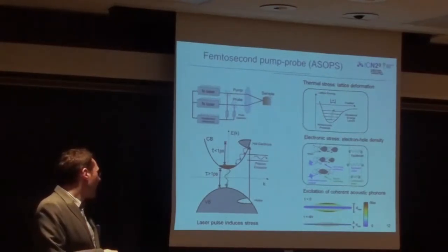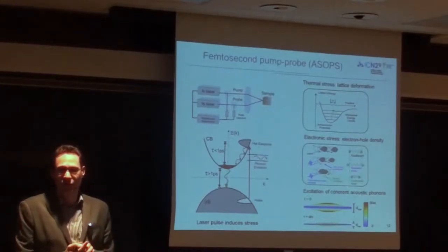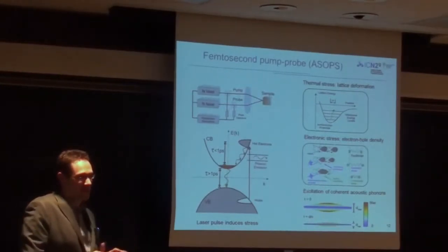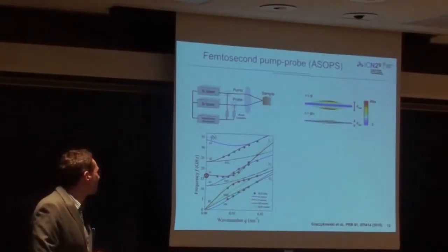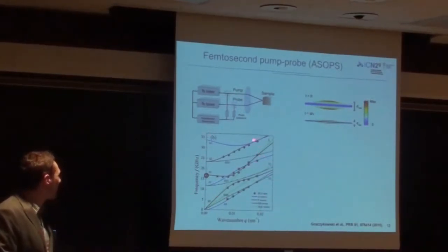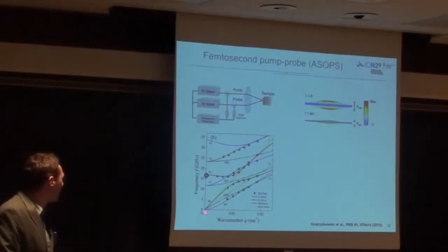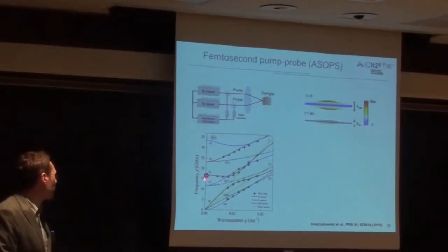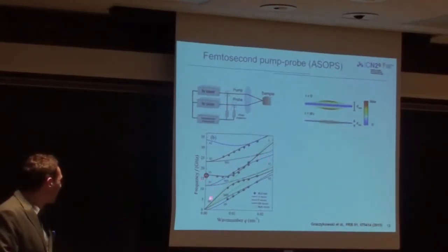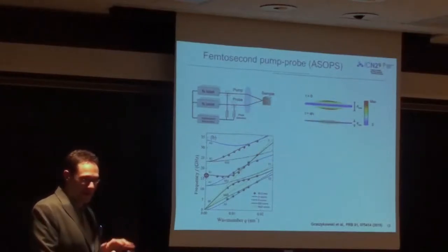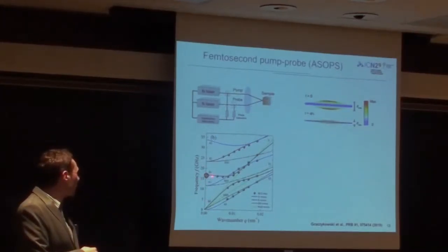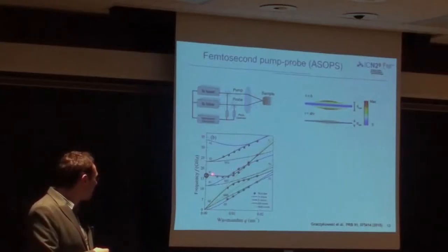And these phonons are, in the first order, leading to a change in the optical cavity thickness of such a freestanding structure. So the question is, what do we actually measure with this experiment? Well, this is a dispersion relation. And it turns out that we are measuring the first order symmetric mode at the zone center, at the gamma point, for k equals 0. So that means here we are at 0, so this we cannot measure. This is an anti-symmetric mode, which is not leading to any net out-of-plane displacement. And so this is the first mode that we can measure,